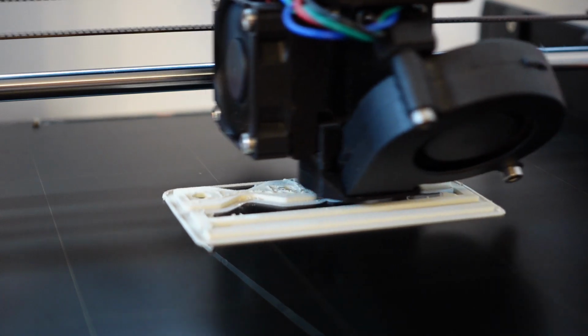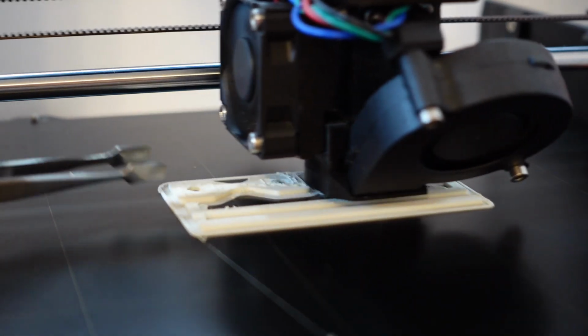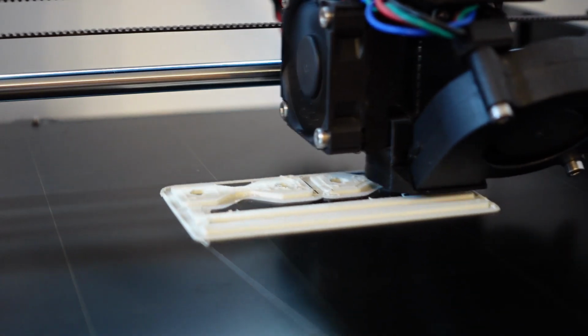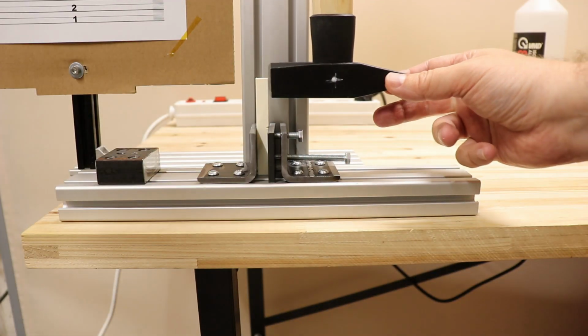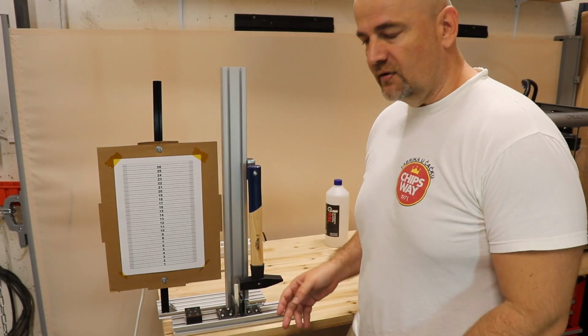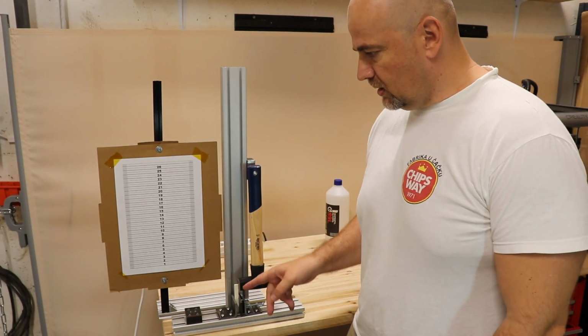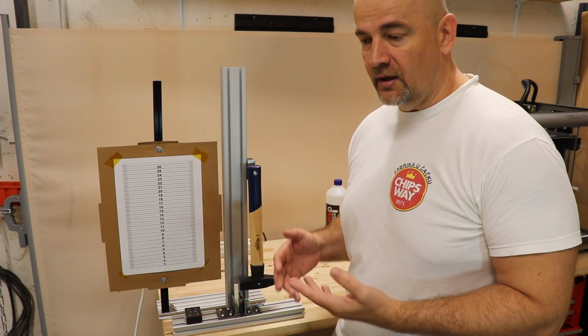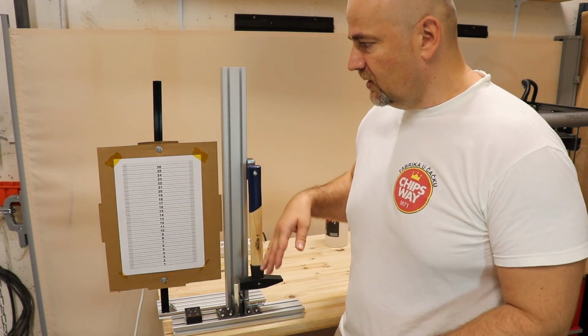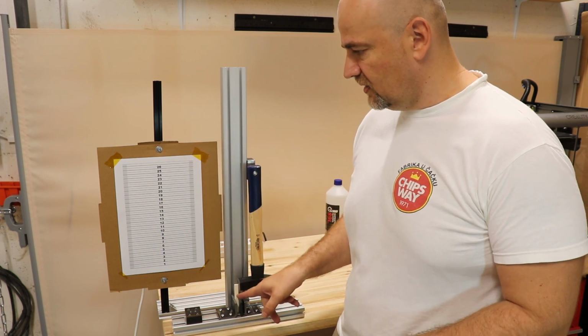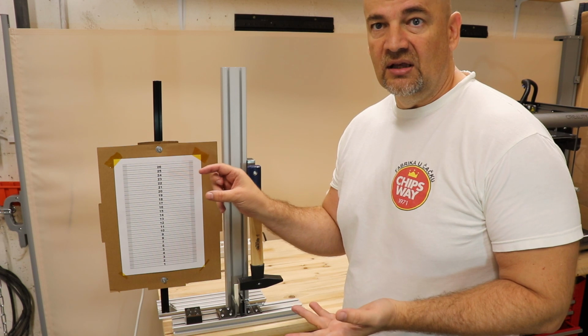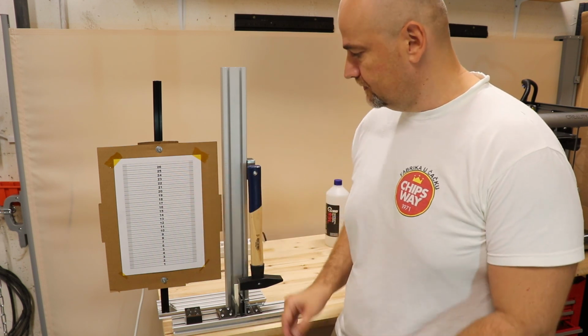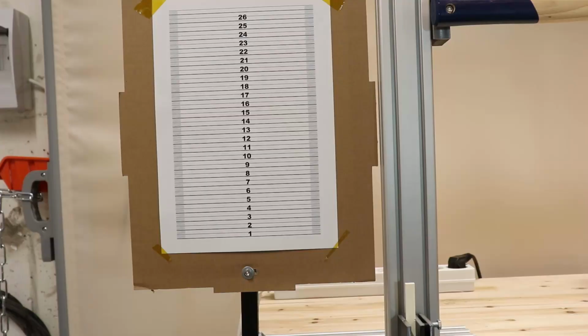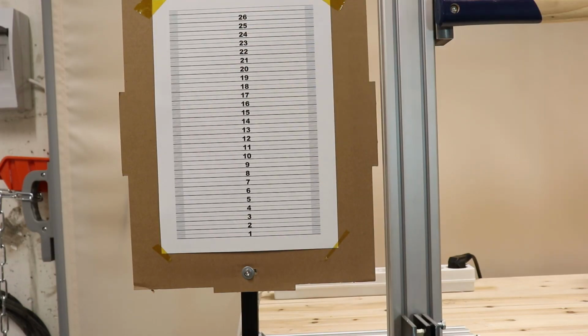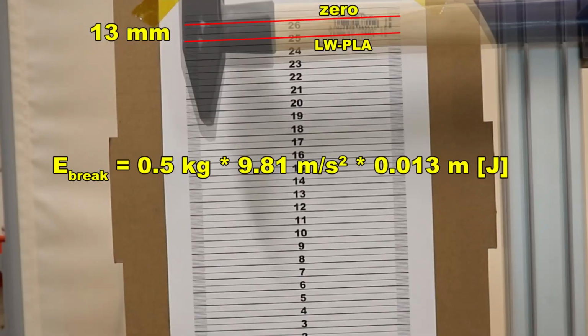And I also printed some other test specimens. These are for horizontal tensile strength, temperature test and impact test. This is my standard impact tester with a half kilogram hammer, and I will see if this material is brittle similar to a regular PLA, then the difference between zero position and swinging after breaking the test specimen will be approximately 20-30 millimeters. Let's find out. This is the position of the hammer after breaking a lightweight PLA, and this is the zero position. And as you can see, the difference between the two positions is 13 millimeters.